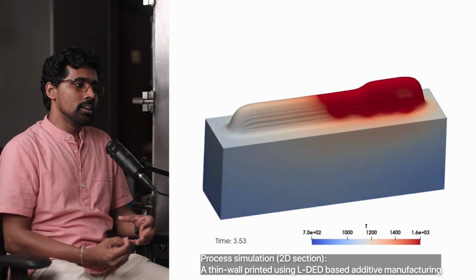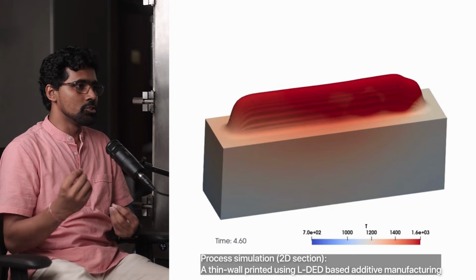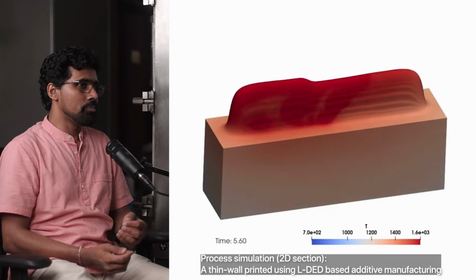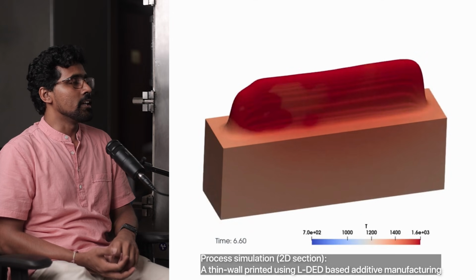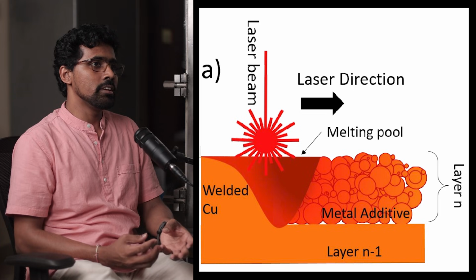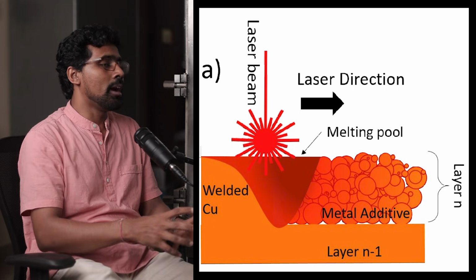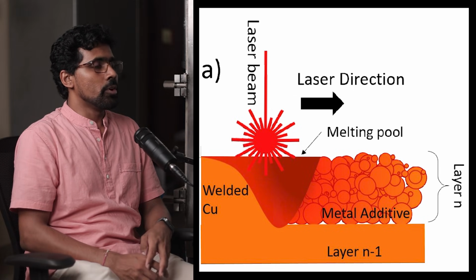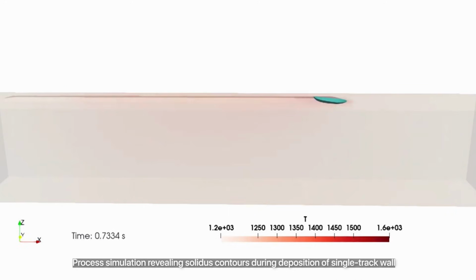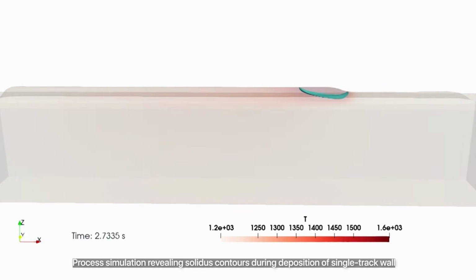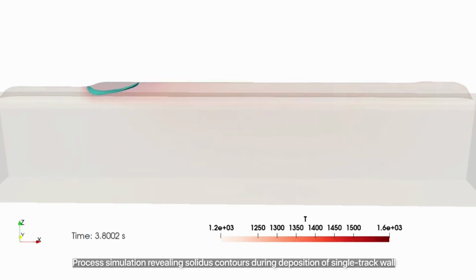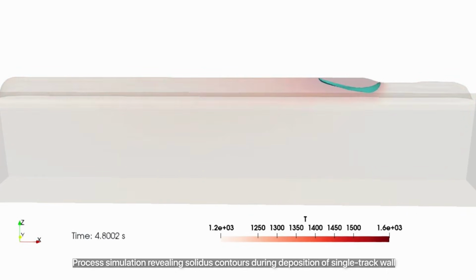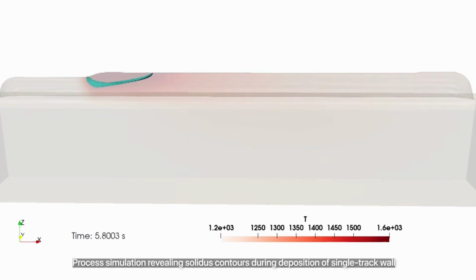And then we try to understand, let's say we are moving the laser at this speed with this power and with this particular powder flow rate, keeping all the other things constant, though there are so many things happening there, then what effect does it have on the solidification? And what is really happening there in the melt pool? That is something we wanted to understand and visualize, and we wanted to create a one-to-one correlation between the simulation and the experiment. In simple terms, simulation is an approximation of a real process. You cannot take into account every small disturbance, the acceleration of the CNC bed, the environment, small impurities. So it's some ideal case.